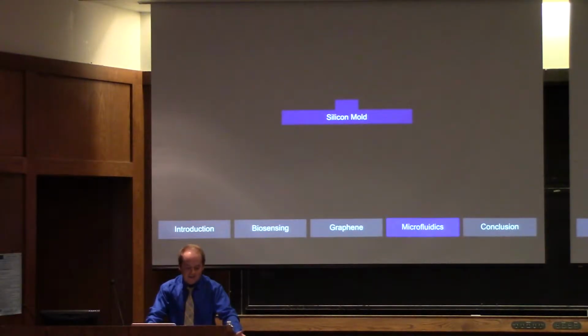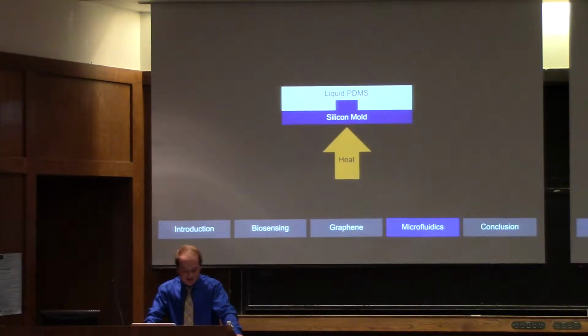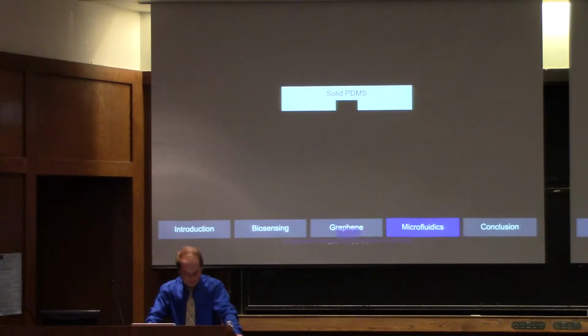Many microfluidic devices consist of a PDMS mold with the channels ingrained on the bottom. Creating this mold is a relatively simple process that involves first pouring liquid PDMS onto this custom mold with the channels already designed on it. Then you heat up the PDMS until it solidifies, at which point you can remove the silicon mold and introduce the substrate of your choice.